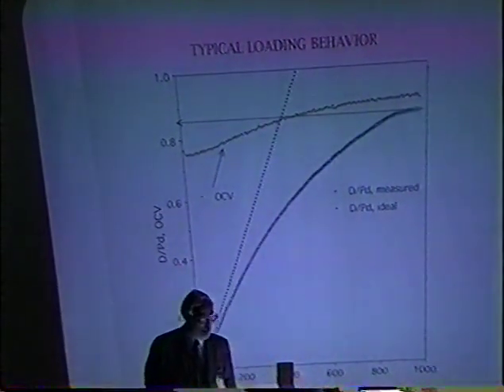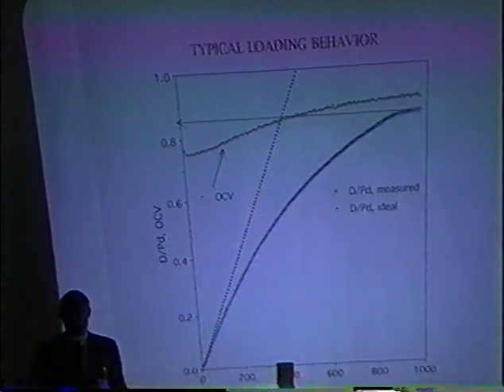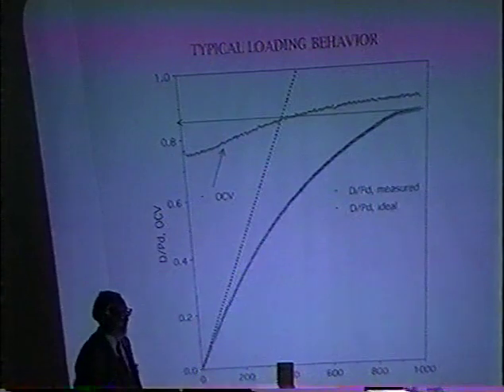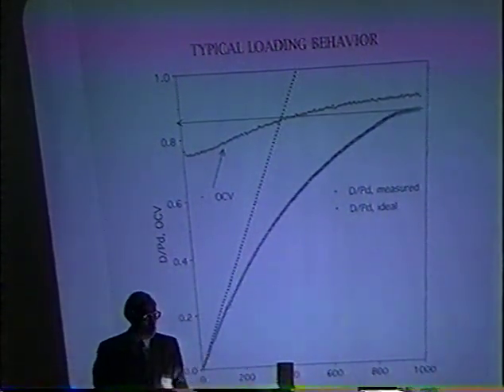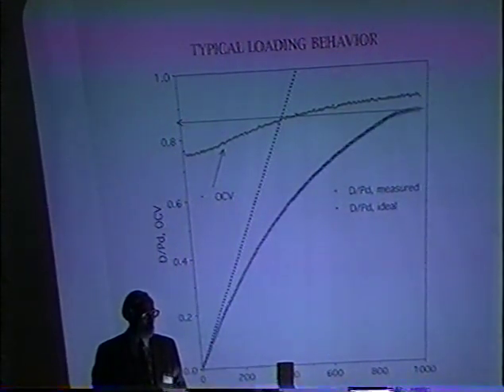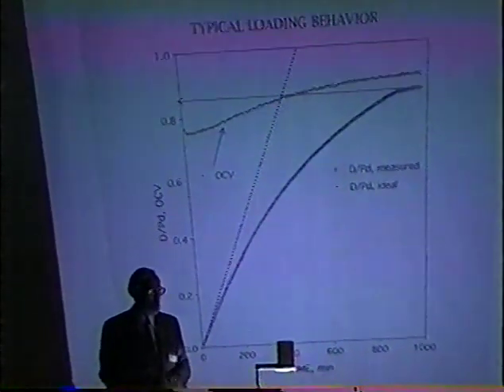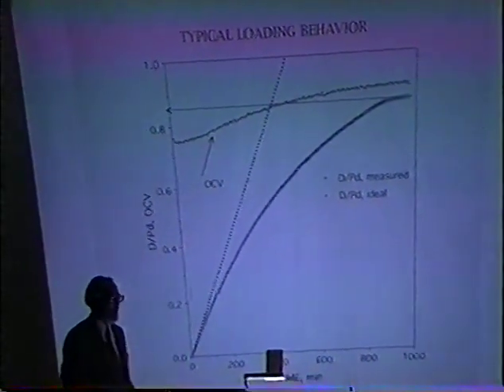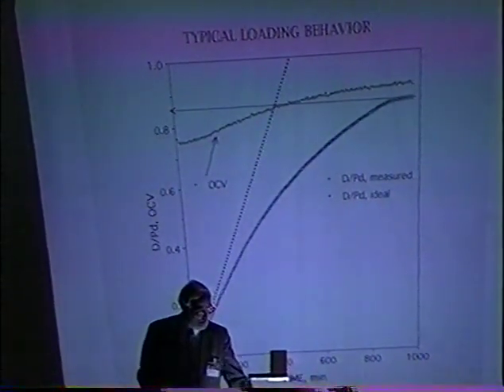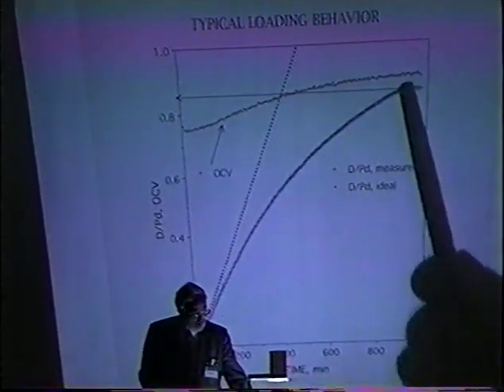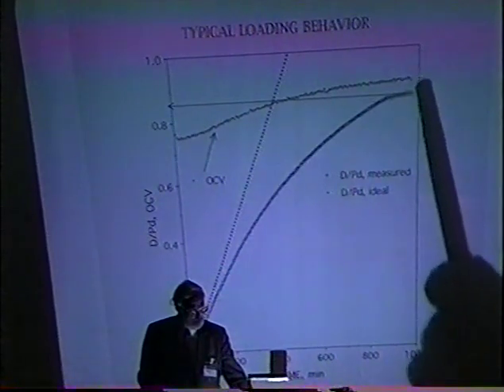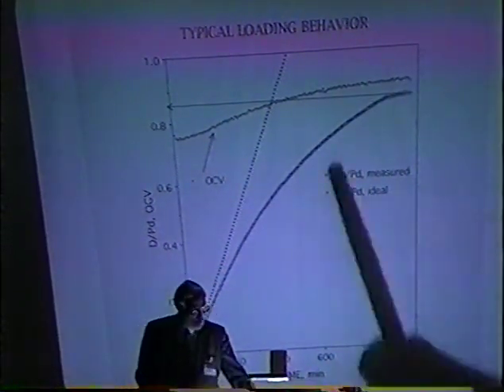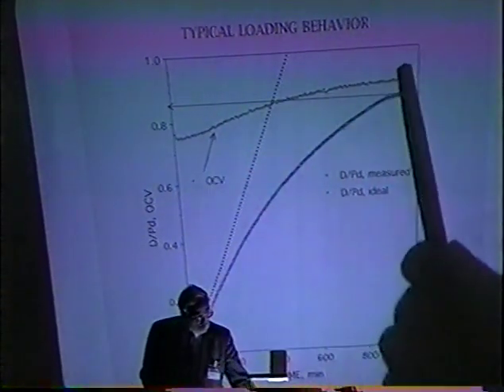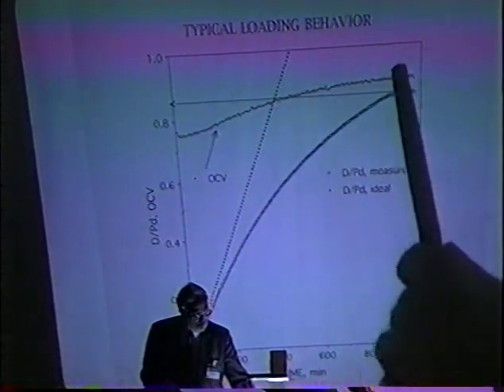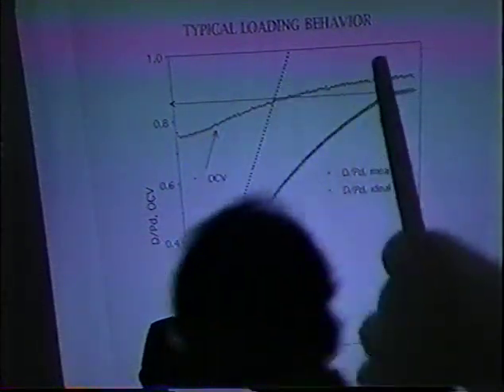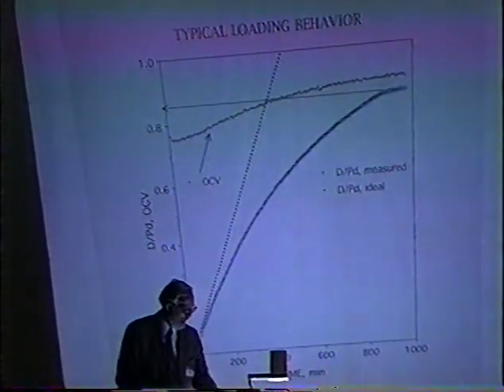Now, the loading. I have adopted a standardized loading technique: fixed current, fixed time, fixed temperature, so as to be able to compare the behavior of these samples without the other variables. I've explored the effect of temperature, time, and current, but I've just chosen an arbitrary one. The loading goes up like this, and then reaches a constant value after some period of time. I do this for 24 hours. The open circuit voltage also rises, and if it's going to make excess energy, this will have to continue to rise. One would expect no excess energy at this low value. We'll get into a little bit of that later.